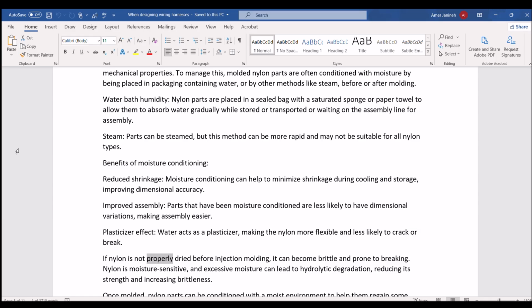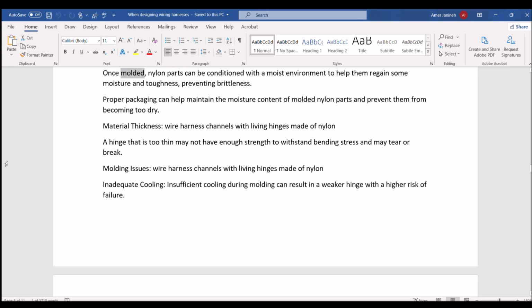If nylon is not properly dried before injection molding, it can become brittle and prone to breaking. Nylon is moisture sensitive, and excessive moisture can lead to hydrolytic degradation, reducing its strength and increasing brittleness. Once molded, nylon parts can be conditioned with a moist environment to help them regain some moisture and toughness, preventing brittleness. Proper packaging can help maintain the moisture content of molded nylon parts and prevent them from becoming too dry.